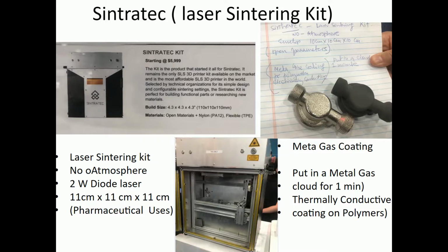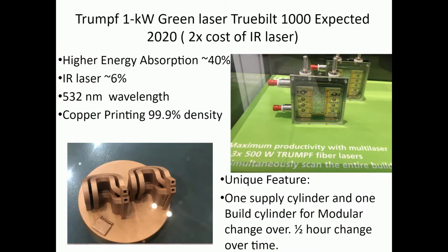The Trumpf 1 kilowatt green laser TruePrint 1000 is expected to launch in 2020. The cost of these systems is about twice the cost of an existing infrared laser. Copper and shiny reflective materials are elusive to laser sintering because of poor absorption. With the invention of the green laser, the absorption rate has increased from about 6% for an infrared laser to about 40% with a green laser. This is a huge improvement in efficiency.